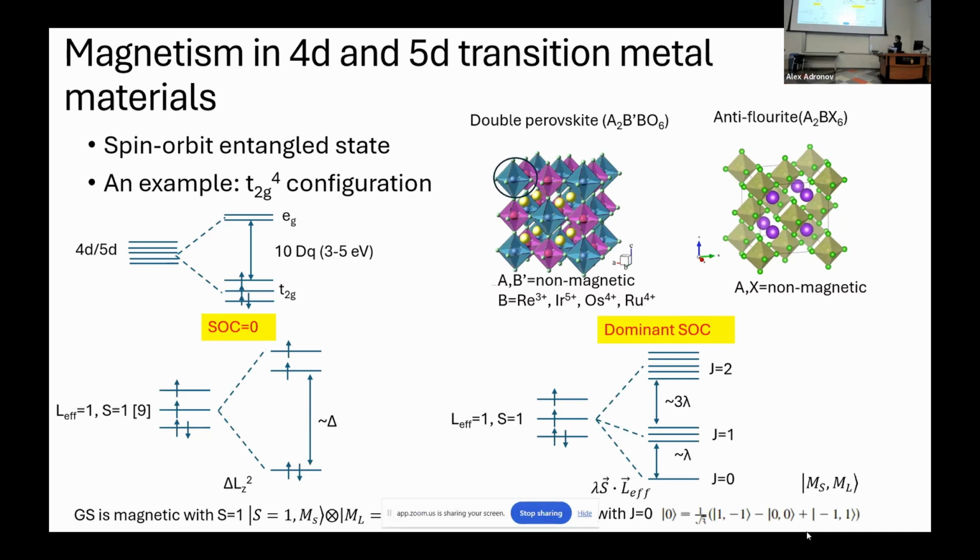So to first order approximation, we just forget about EG. This already reduced the number of states from 210 to 15, which is pretty good. And we can simplify the problem further by arguing that, because the electron repulsion is very strong, we basically follow Hund's rule to fill in the energy levels. So we fill all the up spins first before filling the down spin. At the end, you basically have this lowest Hund's multiplet.